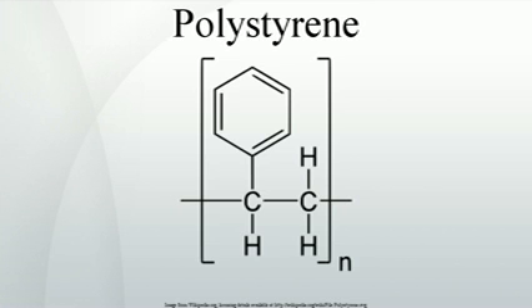In 1941, Dow Chemical invented a Styrofoam process. Before 1949, the chemical engineer Fritz Stastny, 1908–1985, developed pre-expanded PS beads by incorporating aliphatic hydrocarbons, such as pentane. These beads are the raw material for molding parts or extruding sheets. BASF and Stastny applied for a patent that was issued in 1949. The molding process was demonstrated at the Kunststoffmesse 1952 in Düsseldorf. Products were named Styropor. The crystal structure of isotactic polystyrene was reported by Giulio Natta.